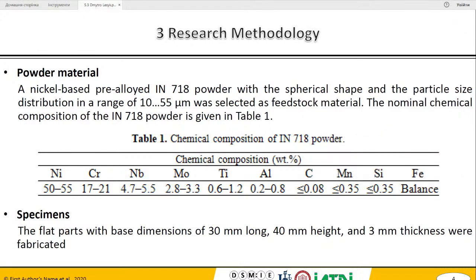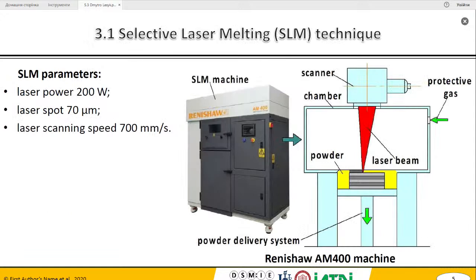So, in particular, in this work, a nickel-based Inconel 718 powder with particle size distribution in range of 10 to 55 micrometers was used as feedstock material. The nominal chemical composition of the powder used is given in table 1. In particular, the flat parts were fabricated by selective laser melting technique using a laser power of 200 watt, laser spot of 70 micrometers, and the laser scanning speed of 700 millimeters per second. General view of the SLM machine and scheme is presented on slide. Next slide, please.